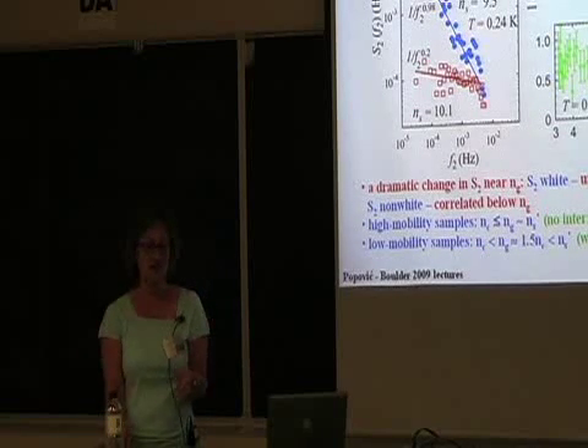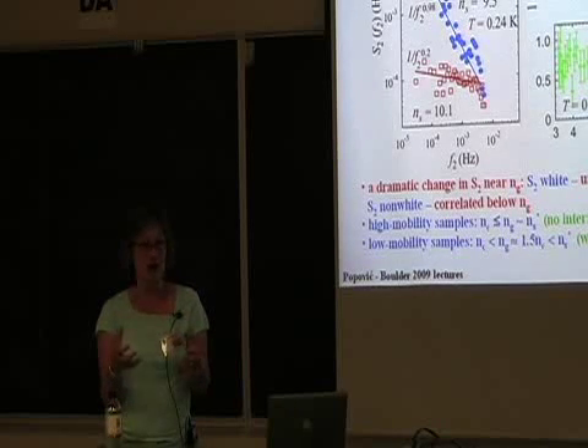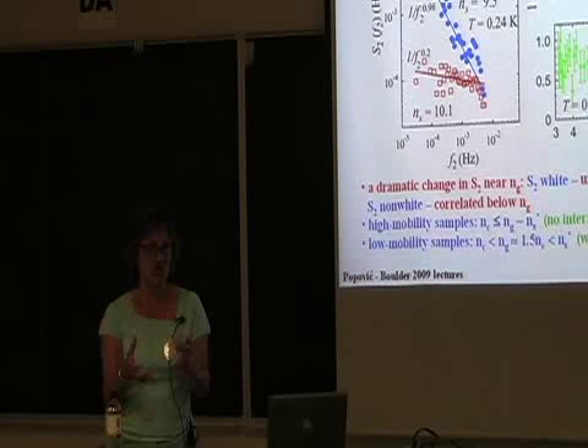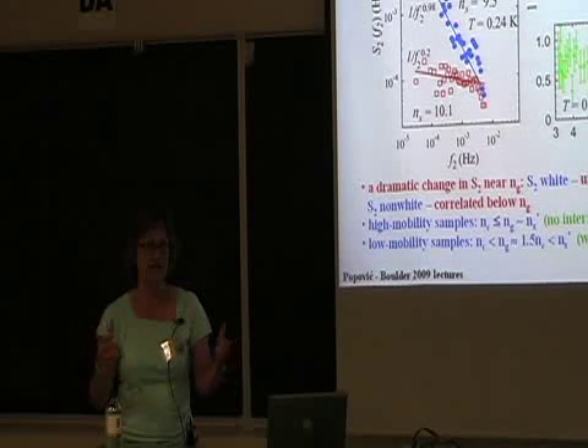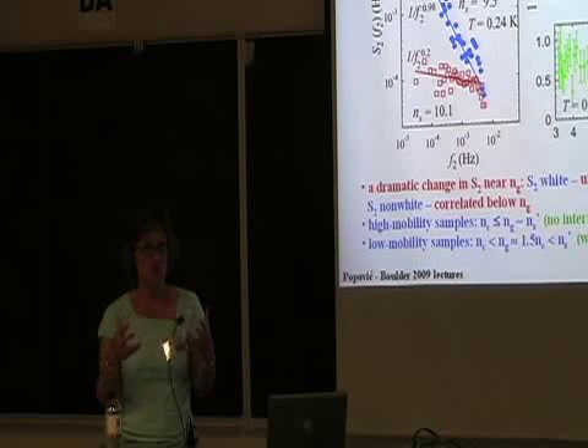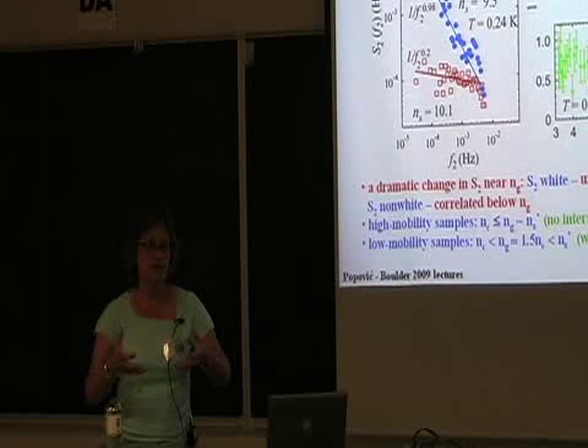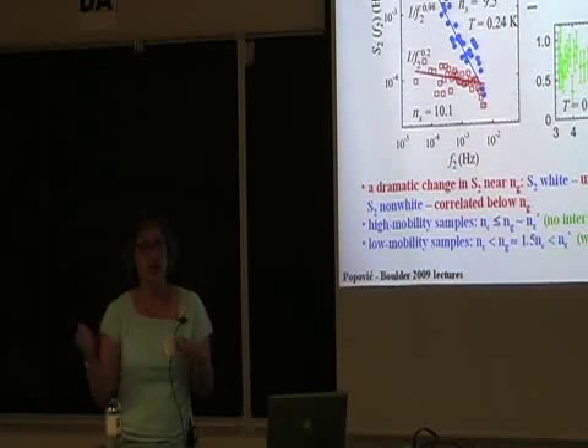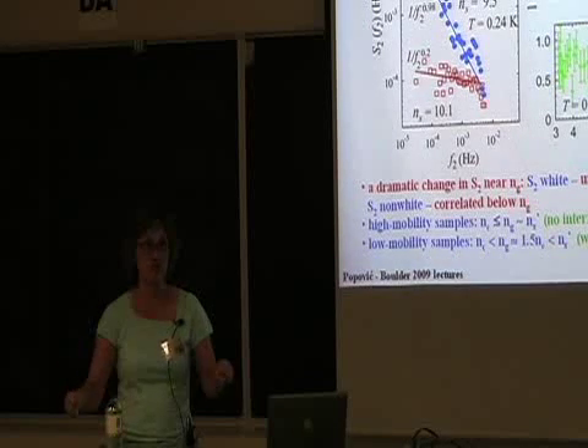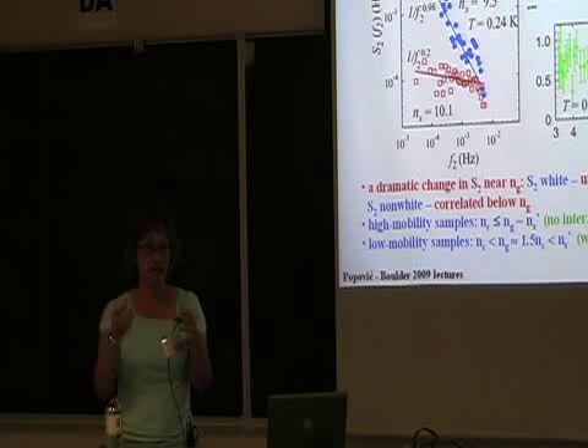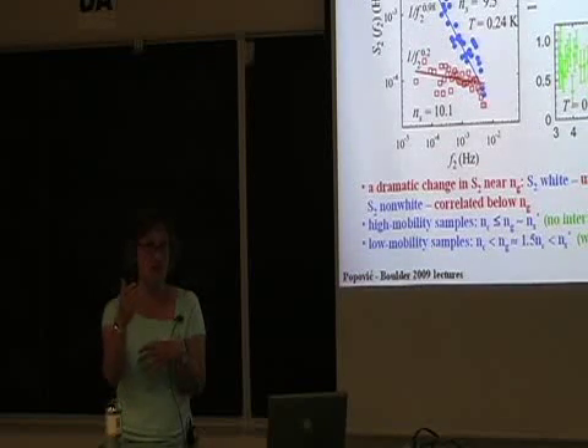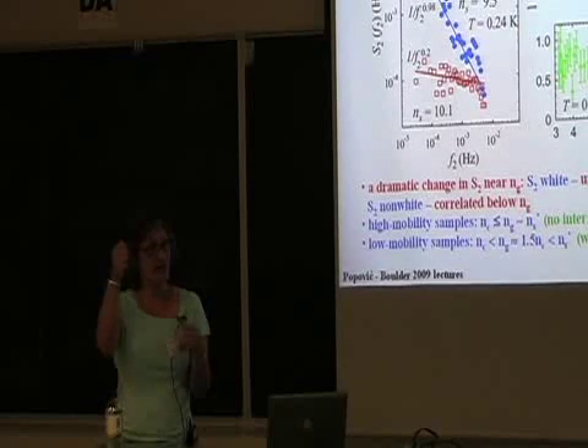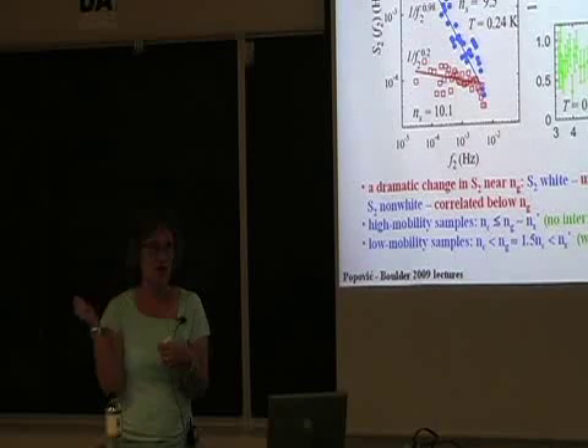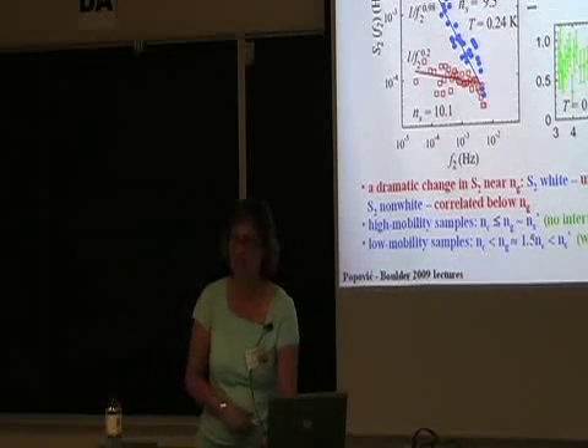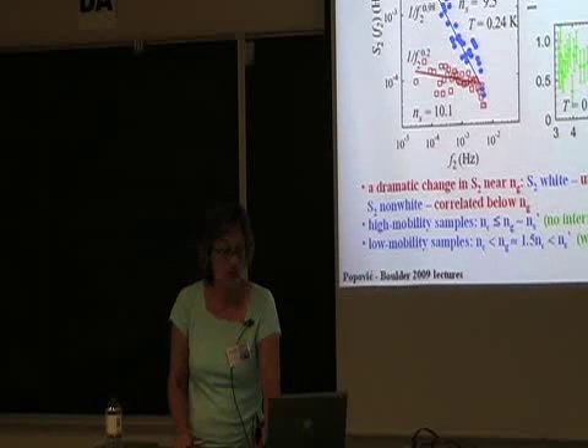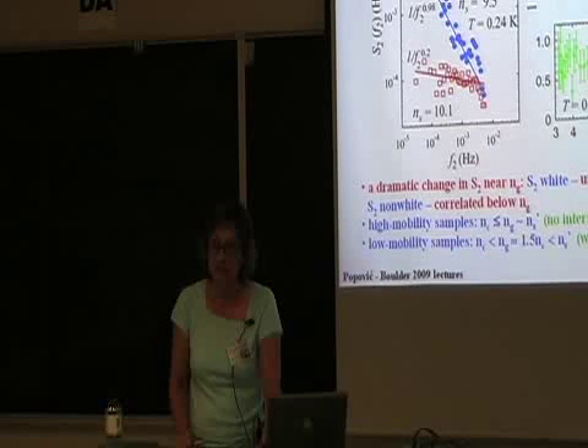Now the other model is the picture of interacting droplets, and they assume that there are short-range interactions there. So you have droplets of different sizes. The low-frequency noise will presumably come from the bigger droplets because they're slow, but they will also be more likely to interact, as opposed to the smaller droplets, which are faster because they're small, but less likely to interact. In other words, the correlations at lower frequencies would be bigger because you're looking at bigger droplets. So this second spectrum would decrease as you increase the frequency. So also, for the high mobility samples, if you apply a magnetic field, that will come later.